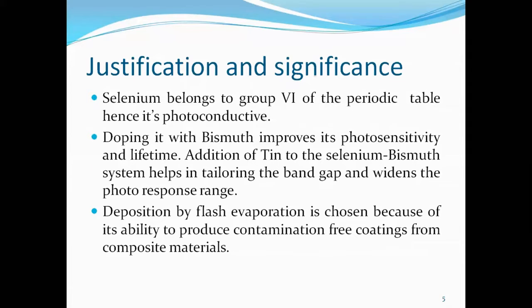But such chalcogenide glasses have a challenge. They undergo aging very fast. Now, that is why doping is important. And for our case, we chose to dope with bismuth, which improves its photosensitivity and lifetime. And we also thought that doing a ternary thin film is better because it widens the photoresponse range. So we chose tin because tin has a special property of helping to tailor the band gap as well as widening the photoresponse range. There are many methods that have been used for deposition.